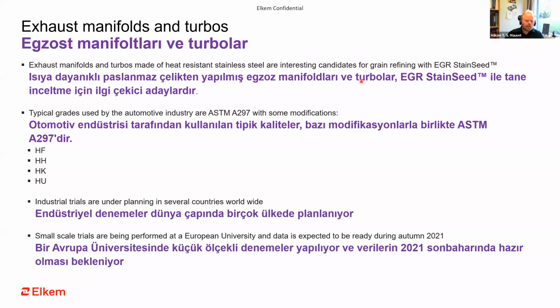Of course, if you look at the typical industrial castings that these grades were made for earlier, they are quite large and thick components, while the manifolds and turbos usually are quite thin-walled. So there is a definite difference there. But the typical grades used by the automotive industry are in the ASTM A297, but with some modifications. It is typically the HF, the HH, the HK, and the HU grade that they use. But often they add some niobium in there as well to get some extra carbides.